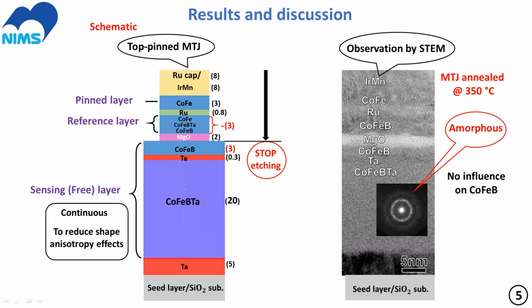This is the only point: we only replace this one. Instead of using nickel iron, we just use this one as the amorphous soft magnetic layer. But the tricky point, as I mentioned at the beginning of my discussion, to fabricate the sensor is that when we etched the pillar, we stopped our etching at the interface between MgO and the free layer, exactly around this interface. And this is because we need to reduce the shape anisotropy effect.